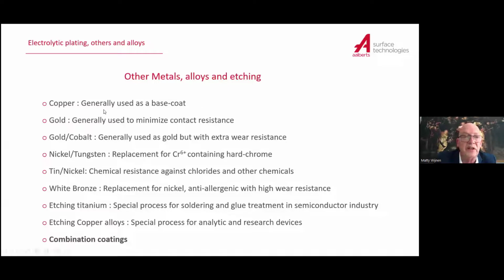We also have the combination of gold cobalt, and then it's an alloy coating. And there you put some cobalt in it, because if you use it for contacts, it functions perfectly, only gold is a very soft material. And due to the fact that it's soft, it wears very quickly. You can put some cobalt in the layer, so we get a gold cobalt alloy, and then you get a better wear resistance.